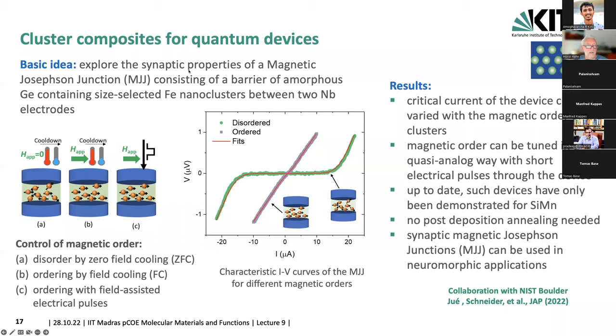So the group of Schneider and Ju are interested in exploring synaptic properties of magnetic Josephson junctions, which consist of a barrier, in this case of amorphous germanium, which contains size-selected iron nanoclusters, and the whole thing is embedded between two niobium electrodes. So here you would see the niobium electrodes, and in between you see the clusters, which are either magnetically oriented or they are magnetically disordered.